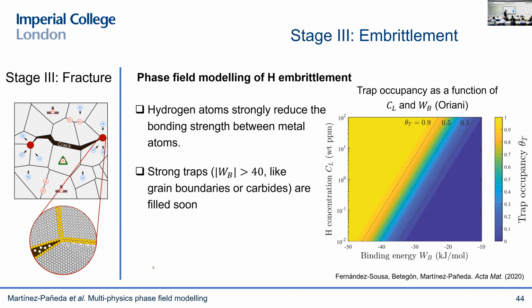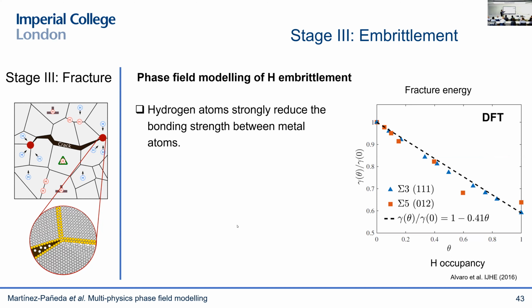And we know from the experiments that grain boundaries are strong traps with binding energies of around minus 40 kilojoules per mole. So you can see that as little as 1 part per million of hydrogen will basically fill my grain boundary with hydrogen. So it is energetically very convenient for the hydrogen to accumulate in those grain boundaries. So if we go back to the atomistic picture, this means that we're going to be somewhere here, and as a result of that, we're going to have a significant reduction in the grain boundary strength.